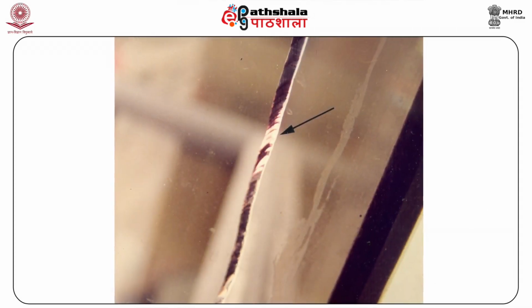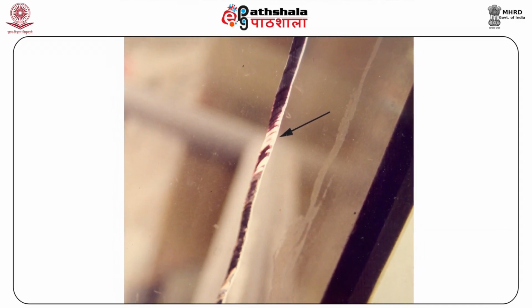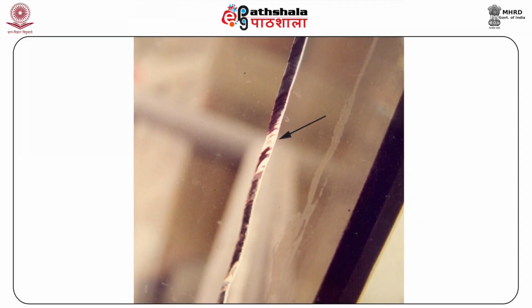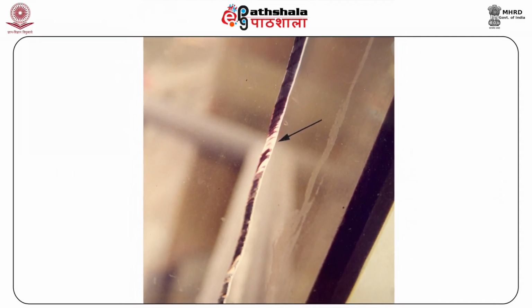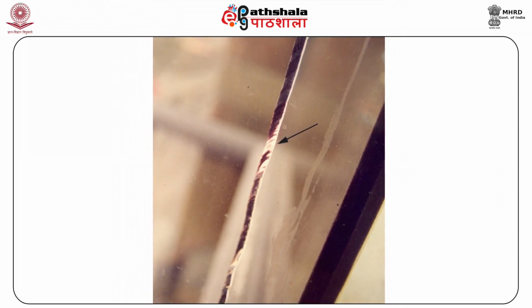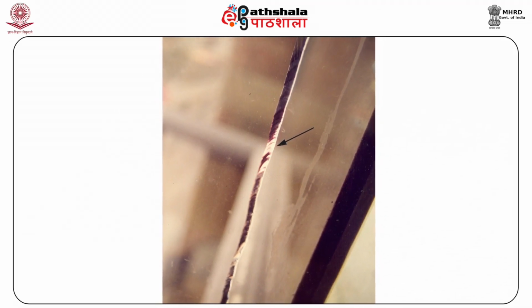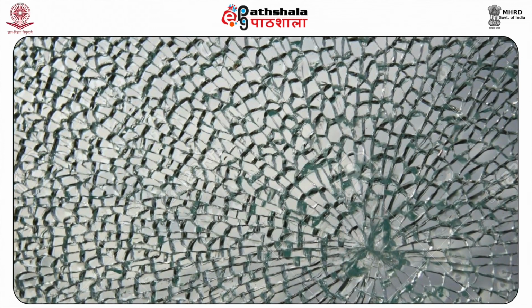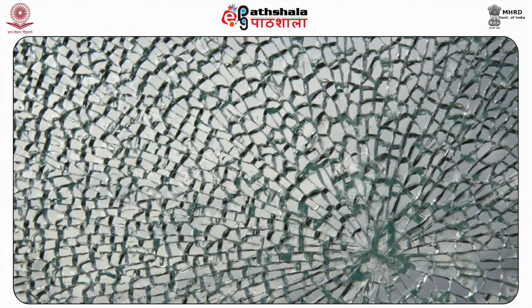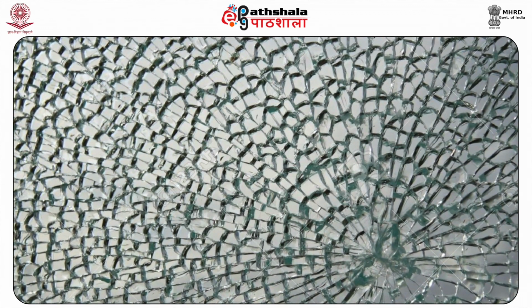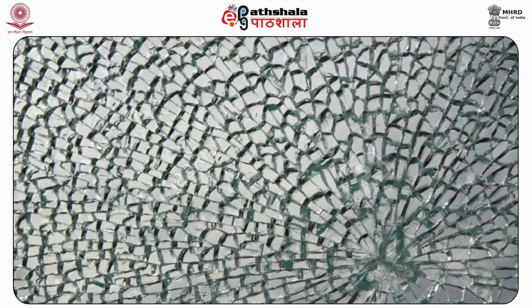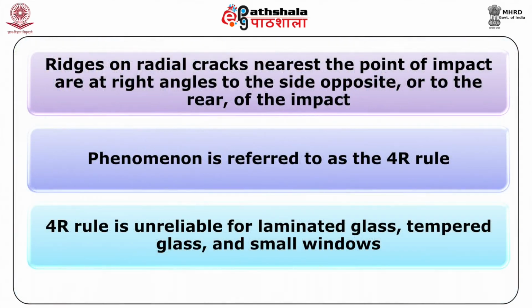By observing the Wallner lines, ridges on the radial cracks, the direction of breaking force can often be determined. Observe only the Wallner lines on the radial cracks nearest the point of impact. If the impact site is not preserved, the glass must be reconstructed. The original orientation of the glass must be known to complete the determination. The ridges, Wallner lines, on radial cracks nearest the point of impact are at right angles to the side opposite, or to the rear of the impact.